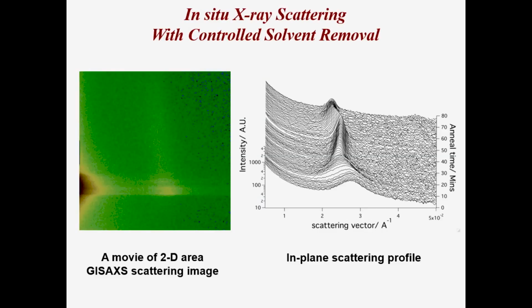And you can follow that. Well, we could follow it, but you've got to believe me, folks. Just believe me again. So this happens to be a film that we swell. We get this beautiful order, and then we start to remove the solvent. What you see happening is that this reflection, which is relatively sharp, begins to broaden as I decrease the amount of solvent. And the period increases because we're removing solvent. Curtis doesn't like me, so we start to stretch apart. But the full width at half max starts to increase.